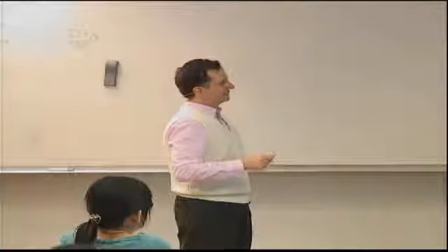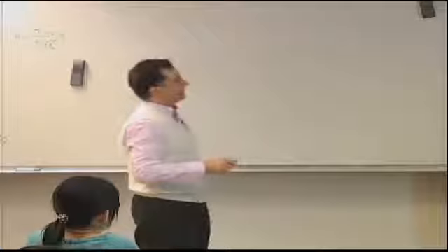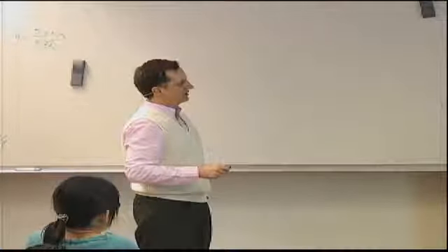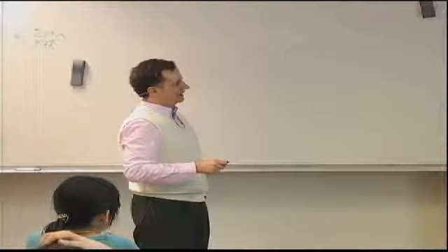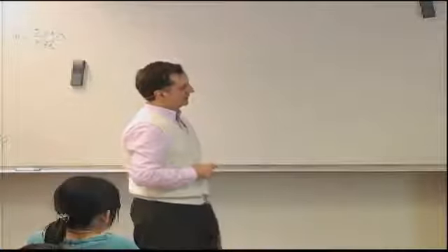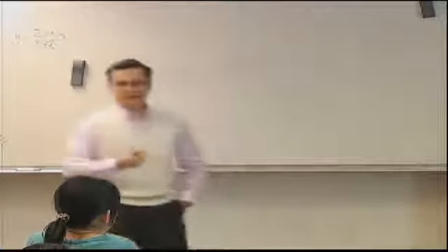The crippling stress equation for one edge free, which is the top of the vertical web, is given by this quantity. And if I translate this to strains, epsilon crippling divided by epsilon ultimate, it's the same as multiplying with ease. So this is the strain at which, given a value of B2, we would have crippling.